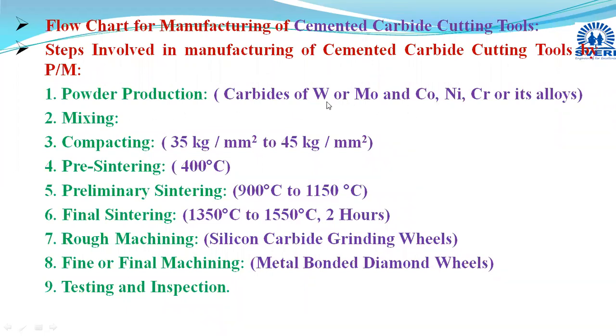Then all these carbides of tungsten or carbides of molybdenum with cobalt or cobalt nickel or cobalt nickel chromium alloys are given to the mixing stage. The second stage is the mixing stage. In this, with the help of different mixing devices or different mixers, it may be blade mixer, screw mixer, or different blenders, double cone blender or Y-cone blender, we obtain a uniform and homogeneous mixture. And here some lubricants are also added. Different lubricants are added. We are using glycerin in alcohol. Then glycerin in alcohol can be used as the lubricant.